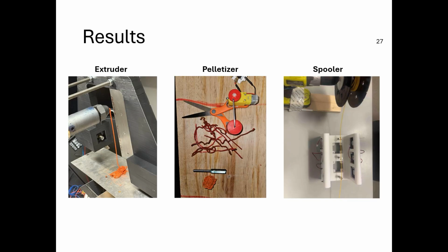Finally, for our results, the extruders worked well to create new filament from shredded material. However, we had many occasions where the barrel would clog, which required proper maintenance to continue testing, as we found that without cleaning the extruder properly, our testing led to very burnt filament, which would also melt and combine with new filament. That would later result in a mix of either different colored or burnt filaments. Even so, with the proper care, the extruder achieved its goal and created filament at our desired diameter of 1.75 millimeters and with the correct color as the shredded material that was used.